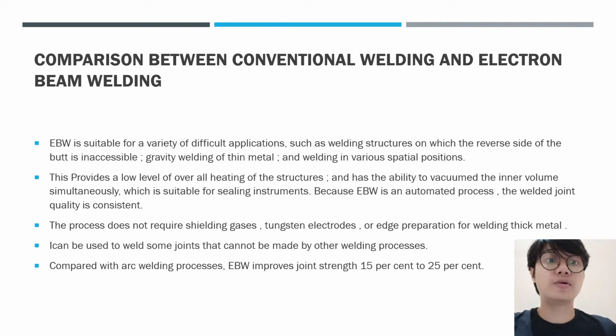Because EBW is an automated process, the welded joint quality is consistent. The third one is that the process does not require shielding gases, tungsten electrodes, or edge preparation for welding thick metal. The fourth one is that it can be used to weld some joints that cannot be made by other welding processes. The last one is that compared with the arc welding process, EBW improves joint strength by about 15% to 25%.